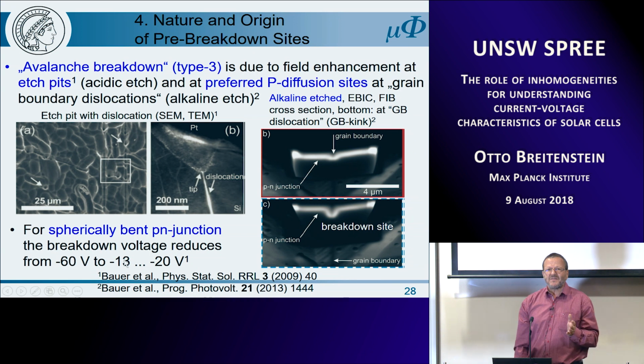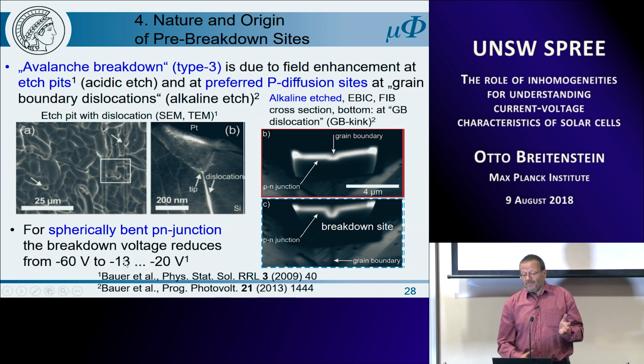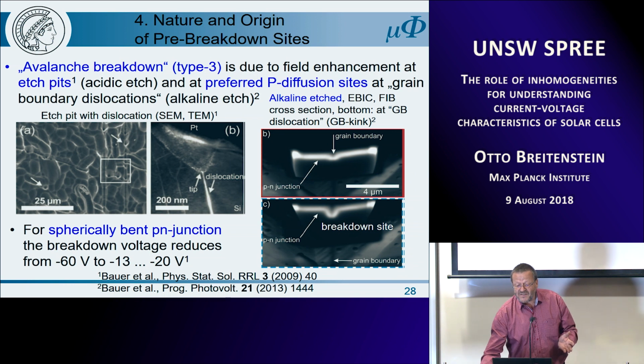And this really explains this. And we also have done these investigations on alkaline etched material, which doesn't show any etch pits. And here we have found that we have preferred phosphorus diffusion at grain boundaries. So this is a grain boundary going vertically.